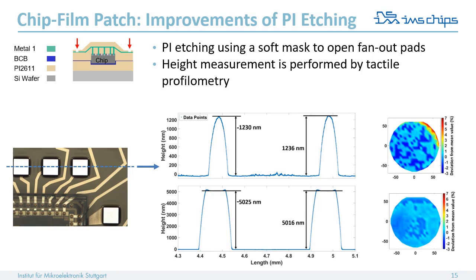Compared to this, the graph below shows the 5 micrometer deep fan-out pad after polyimide etching while using the optimized process. In conclusion, the optimized spin coating process will resolve the problems with polyimide over-etching and avoid damage of the underlying sensitive structures.